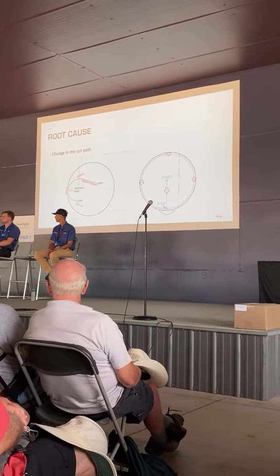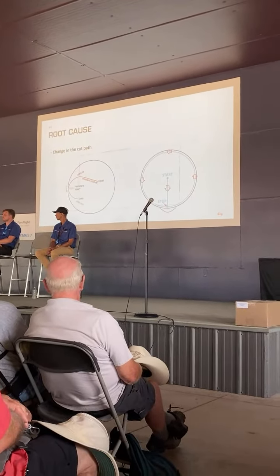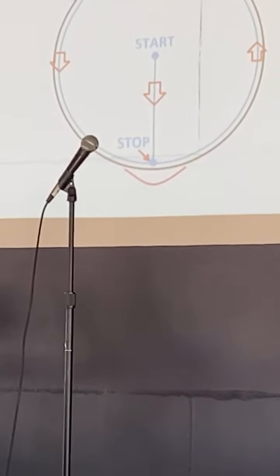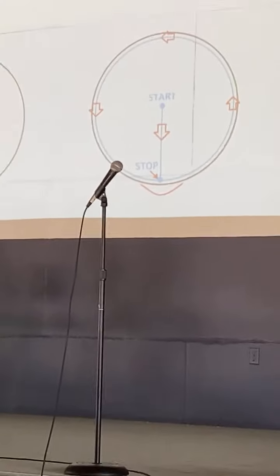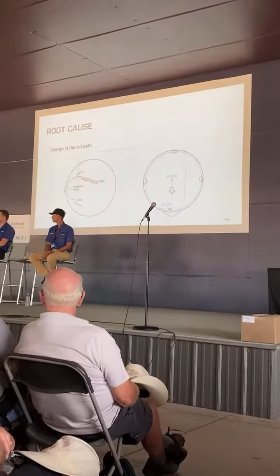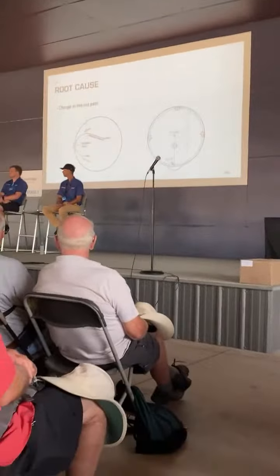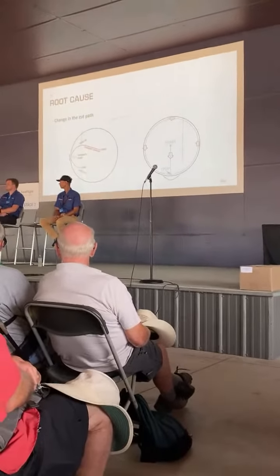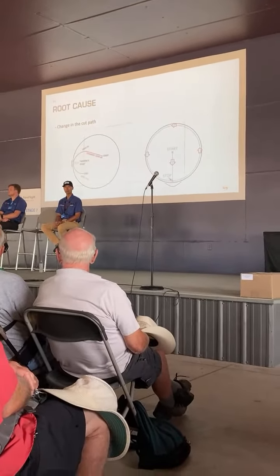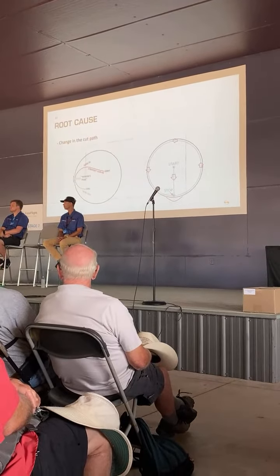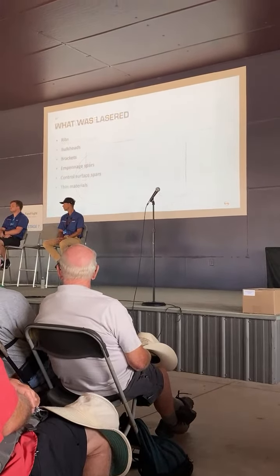As a result, this little red line at the bottom, we can see that there's a heat affected zone. And I've drawn this not necessarily in proportion, but what that does is it heats the edge of the part in a localized area, and then that cools down. And as it cools down, the precipitates gather along a boundary. That does create a zone that could be brittle, and when you dimple a hole, that can cause a crack there to form along that brittle boundary.